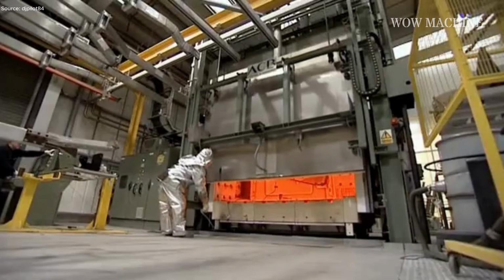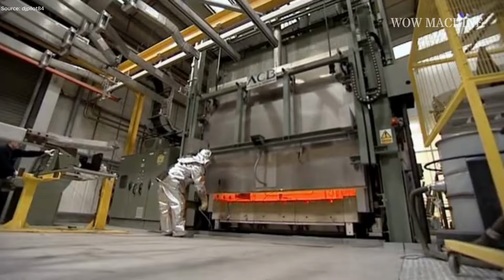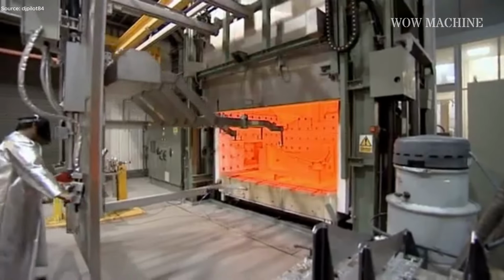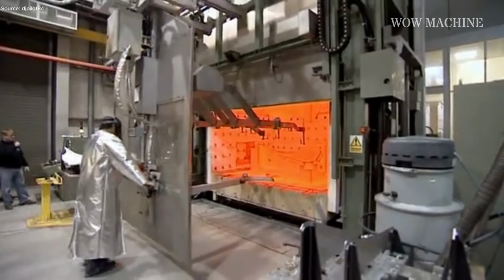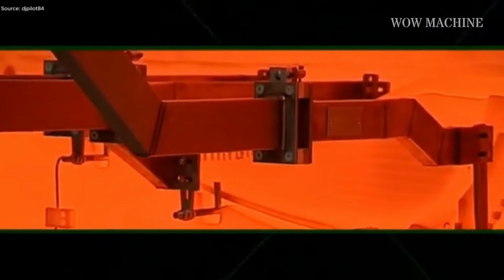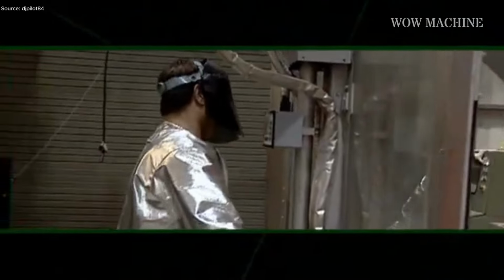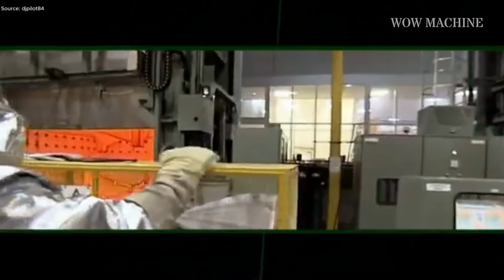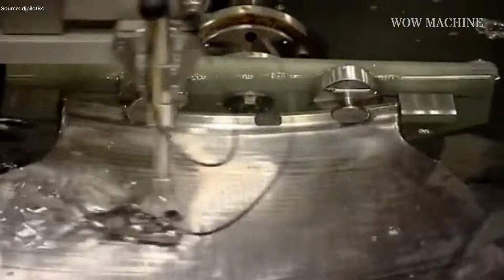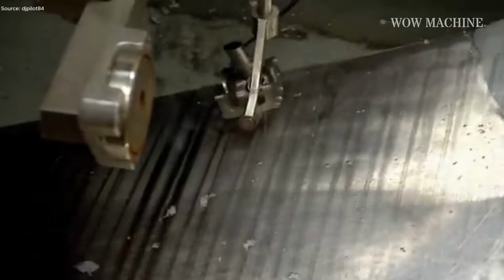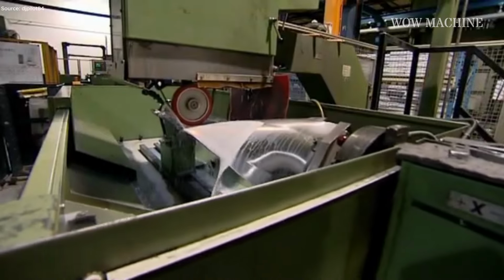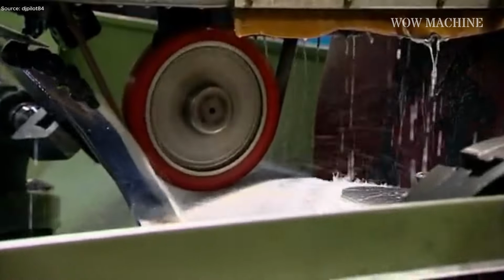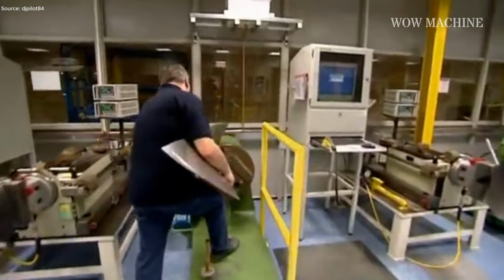The opening step focuses on bonding thin titanium layers into what will become the fan blades. They are arranged in a proprietary pattern before being heated and twisted into aerodynamic form. When inflated with inert gas inside a furnace, the inner walls stretch like elastic steel, forming a hollow yet incredibly strong structure. Even a speck of dust here could ruin hours of work, so preparation has to be spotless. Each inflation takes about 4.5 hours, expanding the blade into its final curve.